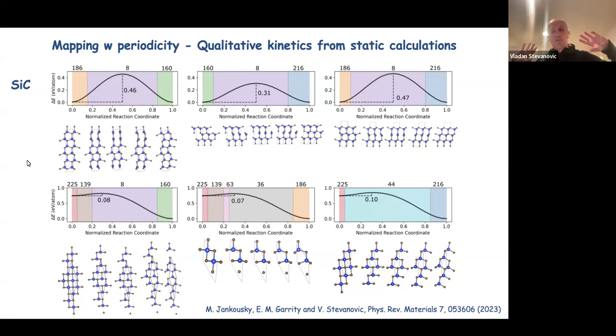And again, we are looking for some qualitative way of distinguishing whether the transformation is likely to be fast or slow. So once this transformation mechanism is discretized, you can calculate, using a first principles method, the static energy of each of these snapshots, each of these images. And what you're seeing here are the energy profiles along these pathways. The 3 upper panels show some estimated barrier for those transformations, and the 3 lower ones have barriers much lower in energy. These are approximate barriers, much lower than the upper ones.